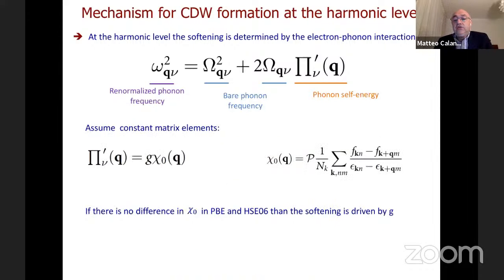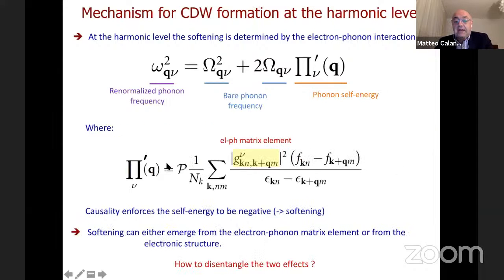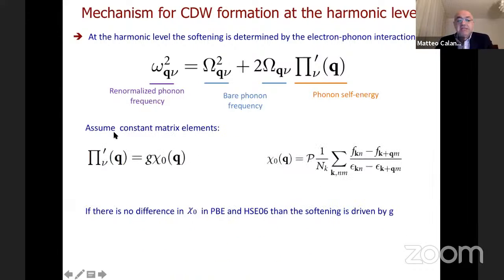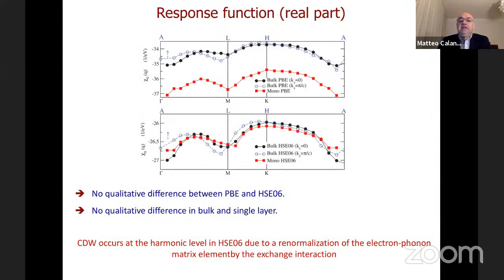In order to understand which one of the two is important, you can, for example, assume for one second that the matrix element is constant, and you take it out from the sum, and you see what happens if you just consider the effect of the electronic structure, that is the so-called susceptibility, K0 without matrix element. You can calculate this very well using Wannier functions. This is the so-called response function, the real part of K0, so K0 prime.